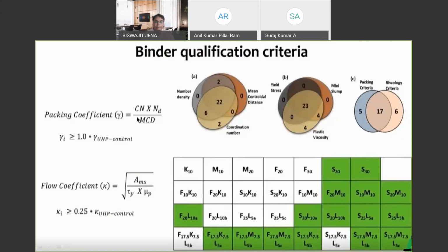There is nothing special about putting in a square root or cube root. So here I have used different Venn diagrams. The first Venn diagram is for packing, and here I get 22 mixtures that satisfy all the criteria. In the middle Venn diagram, there are 23 mixtures from this list that satisfy all the rheology criteria, and I take the intersection of those, and I get 17 mixtures that satisfy both criteria. Those 17 mixtures are shown in green color in the box below.